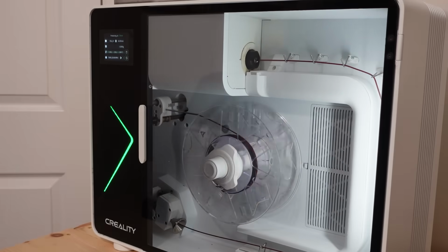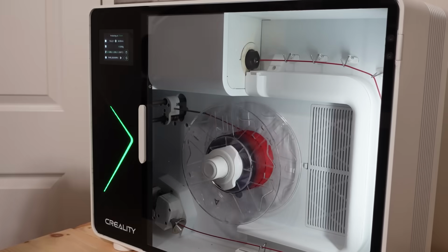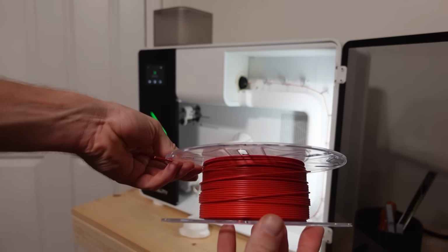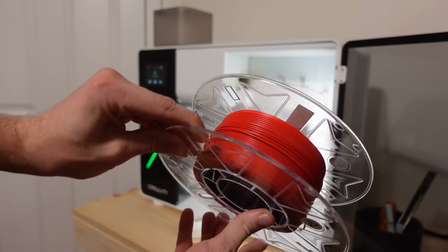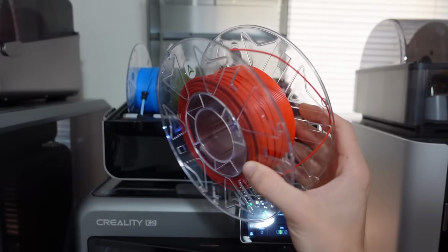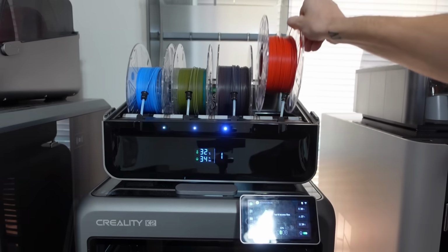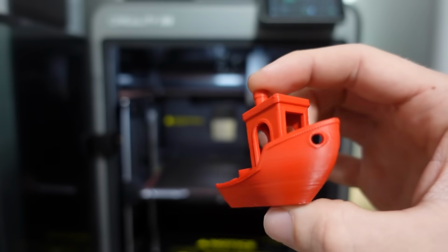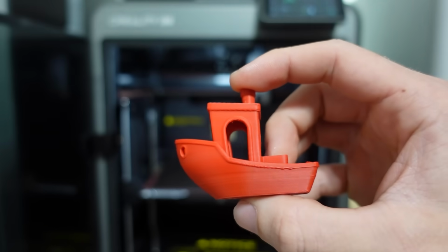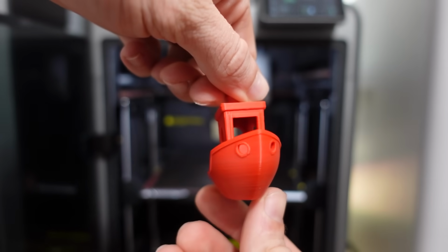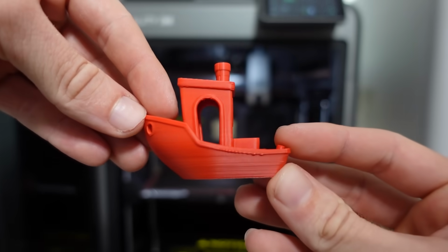After dumping everything into the hopper and letting the M1 spool the filament, the result was a super clean, consistent red filament. Honestly, it looked way better than I expected for something that's almost entirely recycled. So I put this filament into my K2 and the test benchy came out flawless. The print looks like a regular benchy and the red was almost perfectly consistent throughout the entire print.